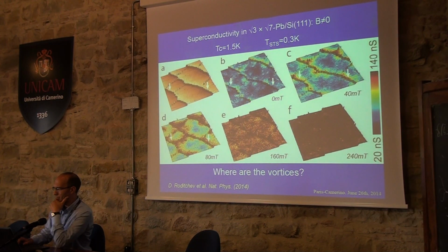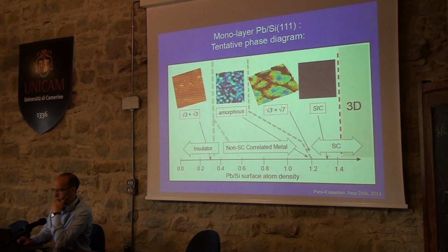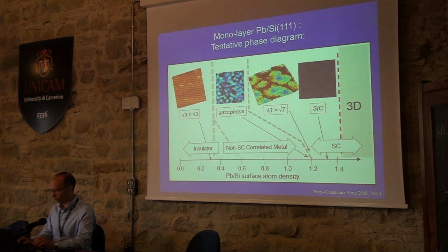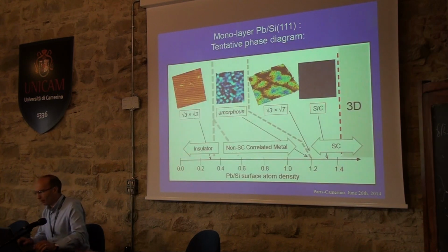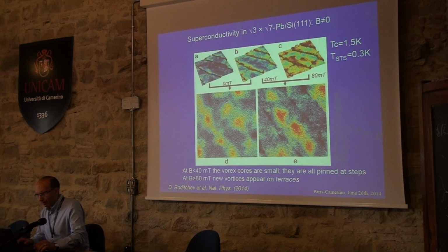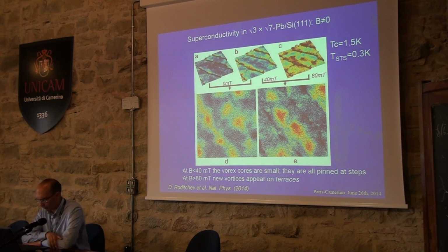Andrea, we will go now further on the next slides. Yes, here, please. So, if you look at this square root 7 by square root 3, simple atomic steps in the superconducting state play the role of Josephson junctions, and Professor Hasegawa will speak about this. If you put in a magnetic field, next slide, please. So here in picture A, I present the superconducting gap plotted in color at zero field. In map B, I present the superconducting gap at 40 millitesla, and you see that the gap is strongly suppressed at the atomic edges.